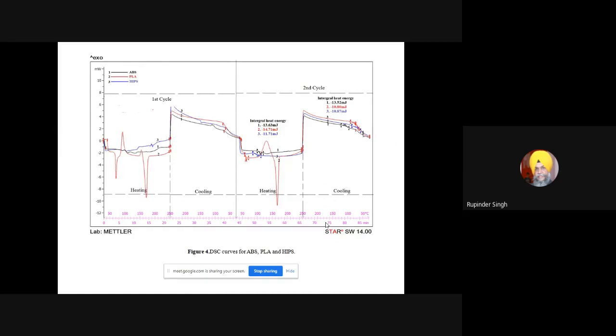Like in our previous case for establishing some smart materials, we try to see their thermal properties. So similarly, we try to see how the thermal properties of this type of material behave. You can see for ABS, in the heating cycle, it was absorbing around 13.63, but in cooling, it was releasing almost the same. Whereas for PLA, there was a loss in the property, like it was taking 14.7, but it was releasing 10.8. So there is a property loss. Similarly, for HIPS, this was almost in an acceptable range. So we can see that PLA is definitely going to degrade, so we have to be a little careful in selecting a particular proportion for this type of analysis.